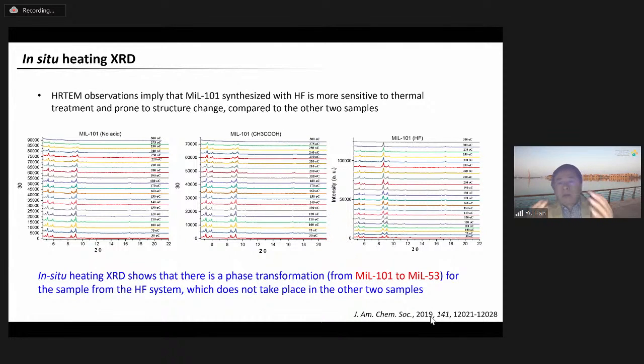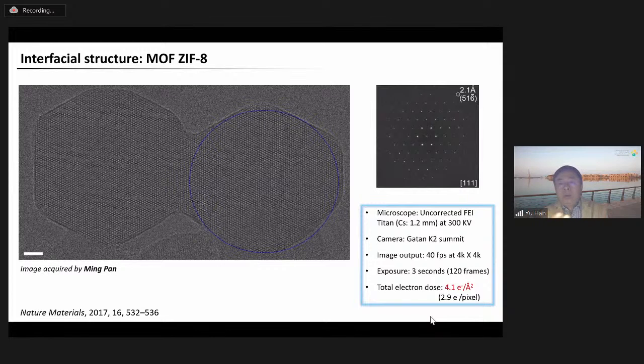So in addition to the surface structure, we have also used HRTEM to probe the interfacial structure formed by assembled ZIF-8 crystals. ZIF-8 nanocrystals tend to assemble through the intergrowth of the 110 surfaces, forming a coherent interface like this. Here is a TEM image showing such an interface. You can see the interface formed between two intergrown nanocrystals. And this image was actually the first ever atomic resolution image of a MOF.